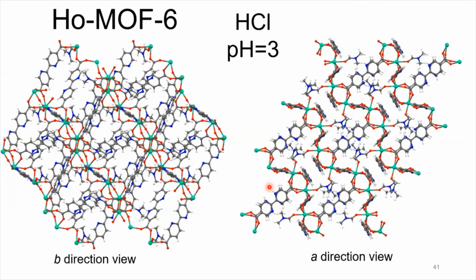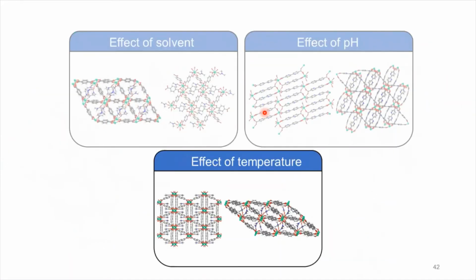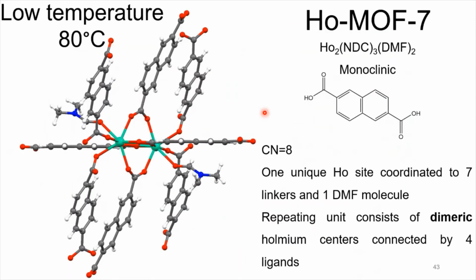Now you can see how it got a little bit messy in there. Bigger chains, but again, non-porous due to the linker in there. But that tells you not only the solvent is important, but your pH control will also definitely affect your final structure. Finally, I'll just want to go into the effect of temperature. So here we were playing with a naphthalene dicarboxylate linker, and we actually observed 3 different structures just by changing 3 different temperature conditions.